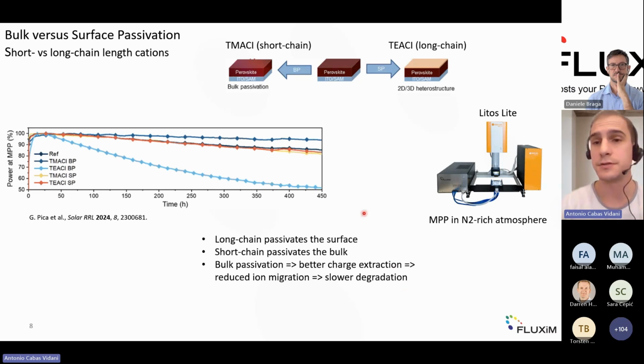And for this, they used indeed Litos Lite, and they performed MPP tracking measurement, but in an N2-rich atmosphere, in order to get rid of any possible influence from the environment. And you see also already the importance of parallel testing, because then you have direct comparison of the stability measurement of devices with a different passivation.